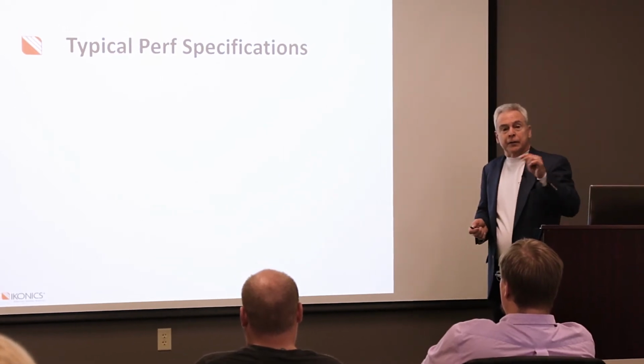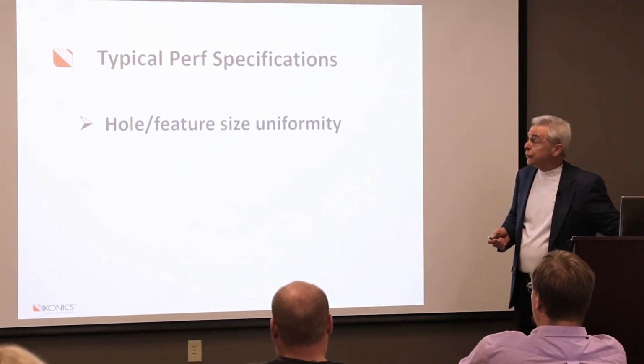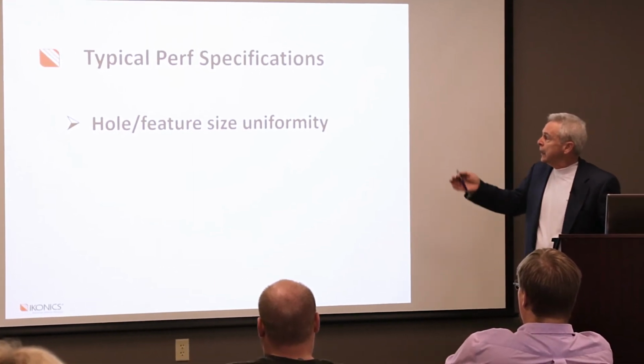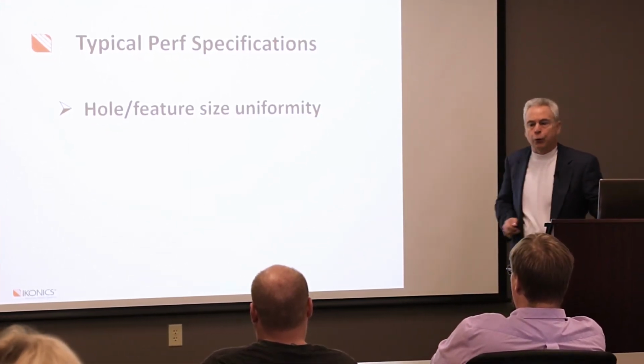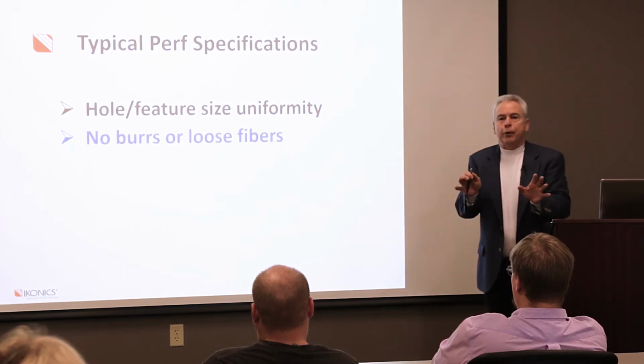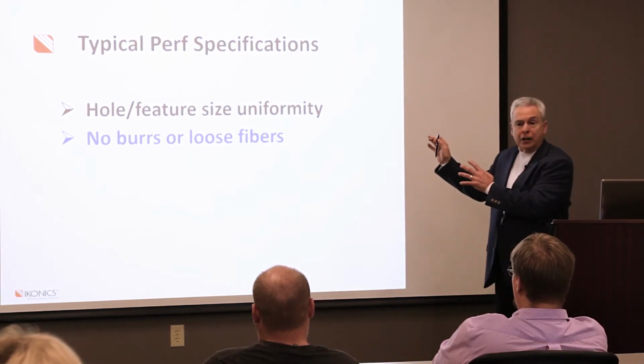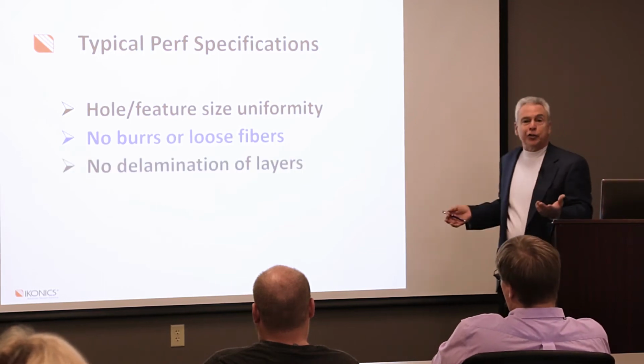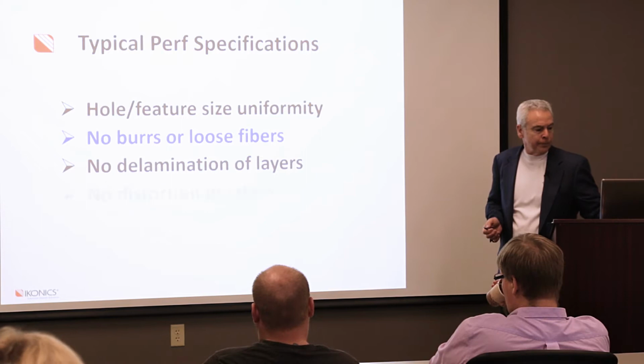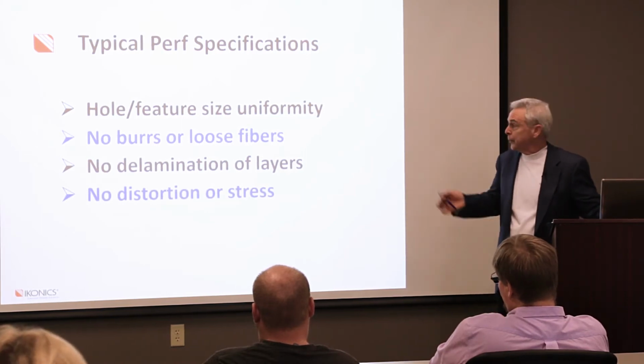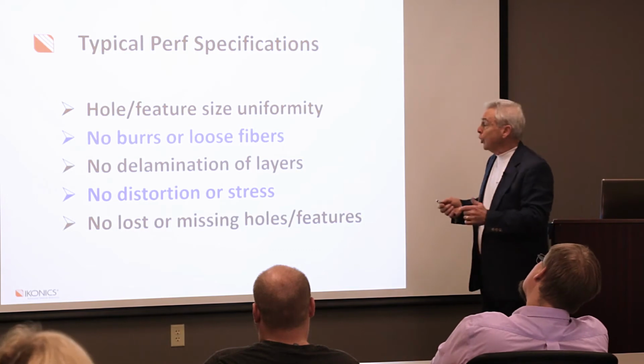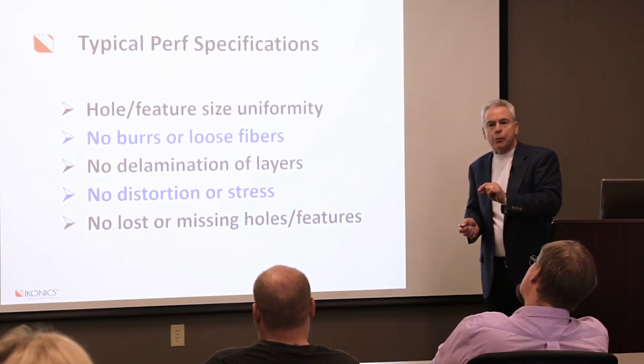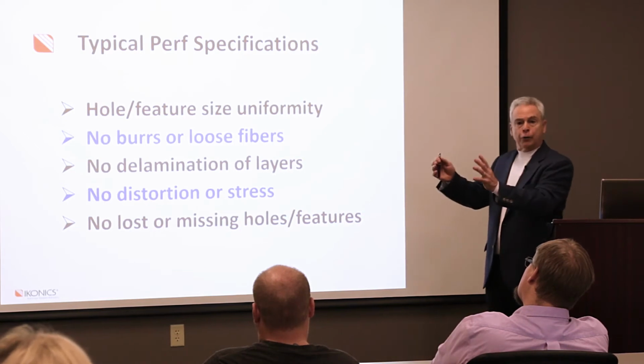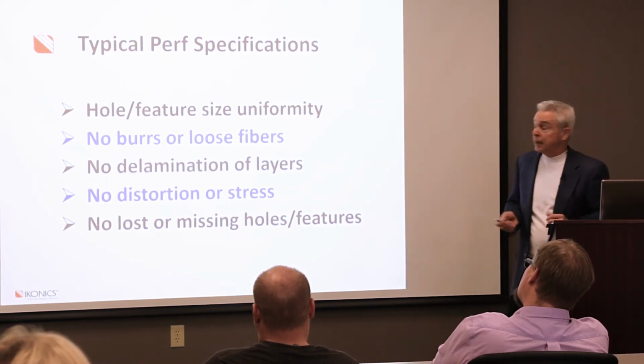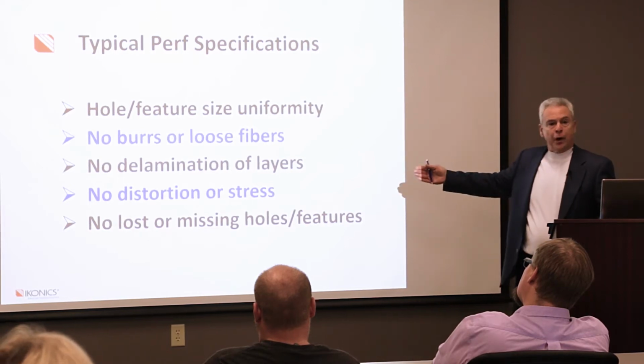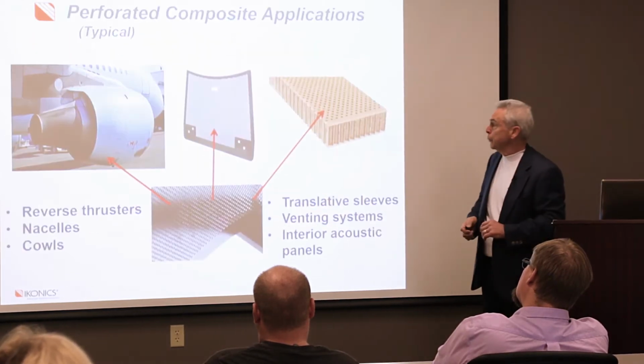Now, ironically, the typical specifications that are often put onto the perforation product is that the holes and the feature sizes have to be uniform. Okay? They can't have any burrs or loose fibers, and we just talked about that as a challenge before. No delamination of layers, again, a challenge with traditional methods. And no distortion or stresses built up in the composite. No lost or missing holes or features, which often does occur with traditional methods. In other words, you don't have all the holes or features that you want in the composite. Okay? So that is a specification that is required by the aerospace industry for perforating composites.